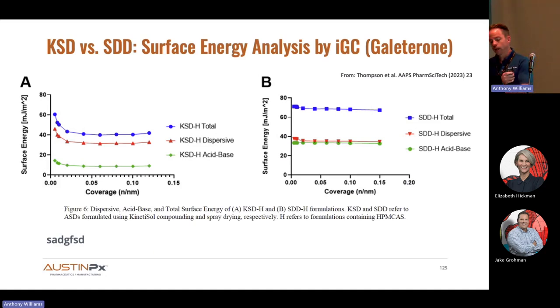We just published a paper with our collaboration with UT, looking at galeterone. Stephen Thompson did this research, and he looked at surface energy analysis by inverse gas chromatography for KinetiSol dispersions in HPMCAS-H with galeterone versus the spray dried equivalent. What was interesting about this study was that, as you can see between the left and right panels, the surface energy of the KinetiSol particles, particularly acid-base surface energy, is substantially lower than the spray-dried particles. And I think this is really interesting and something that we're just starting to think about.